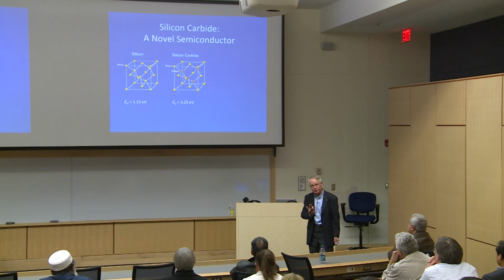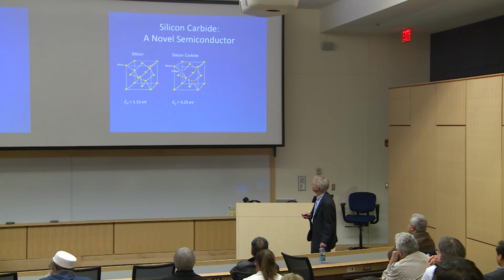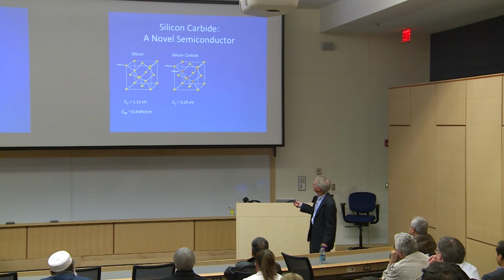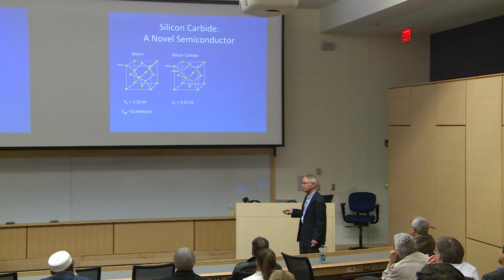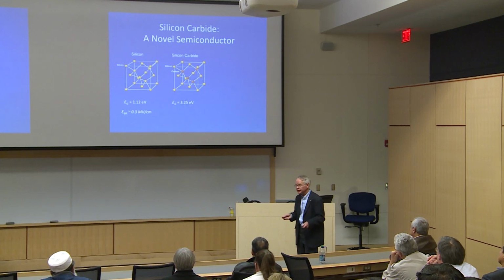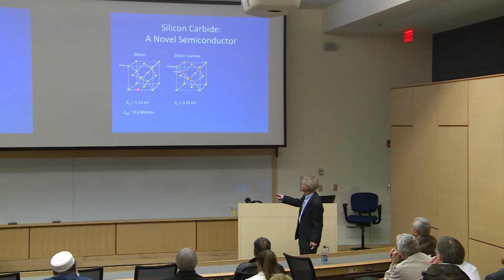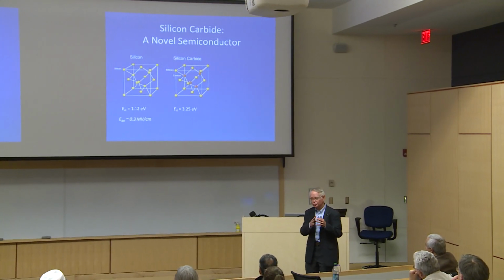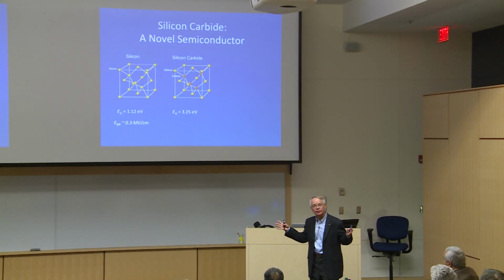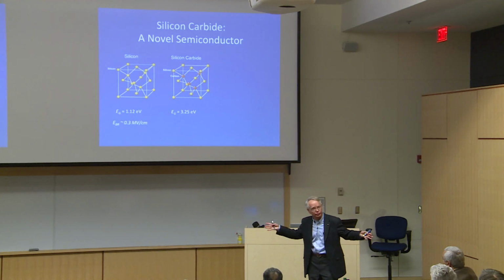The other parameter that's really important here is the breakdown electric field. In silicon, the breakdown electric field is 0.3 megavolts per centimeter. This is the electric field that's enough to start tearing these bonds apart. When that happens, you get a huge number of carriers. You can't control the current flow. It just electrically breaks down.